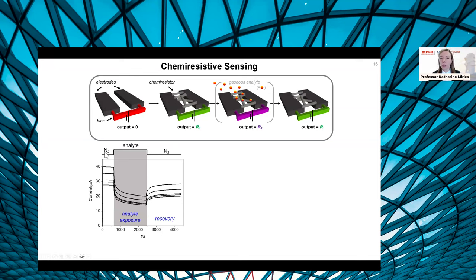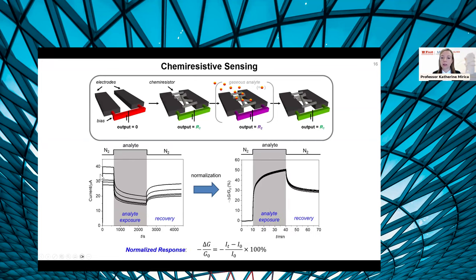So we take this raw data of current versus time, and we typically convert it and normalize it into relative changes in conductance that we plot in such a way that they're proportional to resistance. So when you see this vertical axis labeled as so, just think of that as resistance changes. So in this particular case, the resistance increases upon exposure to the analyte, and then we see partial recovery with analyte removal.